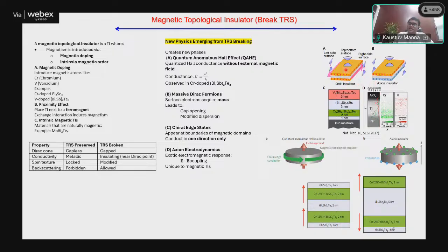If there are no ferromagnetic layers, then the in-between layer is a topological insulator, and we had the protected edge states, both the crossings. But if you polarize both the ferromagnetic layers in the same direction, then because time reversal symmetry is now broken, one of the layers will be gapped, whereas the chiral edge state associated with the up spin only will survive. So you have one edge state, the same picture as the quantum anomalous Hall effect. Now the edge state will give the quantized conductance of e squared by h.